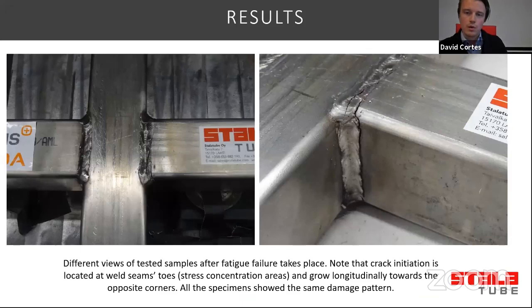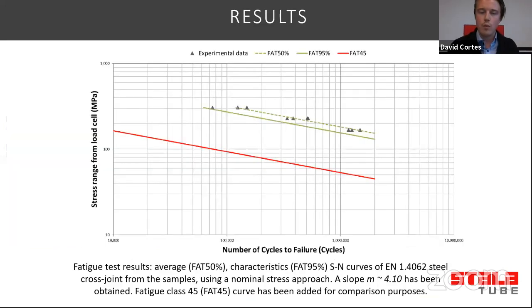I'm going to show you this because you can see that these welds have not been ground. So there's still room for improvement. And also you can see the crack initiation point, that it's on top of another weld joint, on top of each other. So the mechanics of the fatigue crack is a hotspot crack. And so we can use the hotspot calculation here. So we made 9 tests and made the FAT curve based on those.